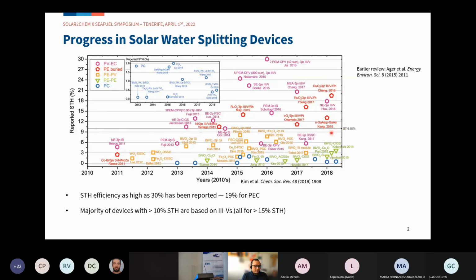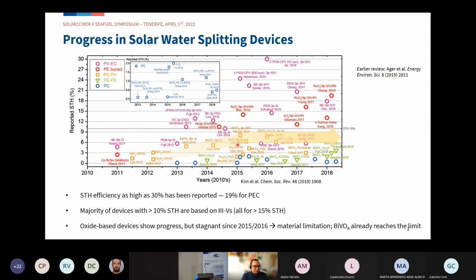The other thing that we can take a look at here is the solar to hydrogen efficiency 10% line. Above that line, most of the devices are actually based on III-V semiconductors. If you take a look above 15%, then exclusively all the devices are based on III-V semiconductors. And one can argue whether this is scalable or not. I think Sophia later will probably talk about that as well. But on the other hand of the spectrum here, we have oxide-based devices, which are arguably more scalable. We saw significant progress at the beginning, but the reported solar to hydrogen efficiency has been stagnated for a few years now.